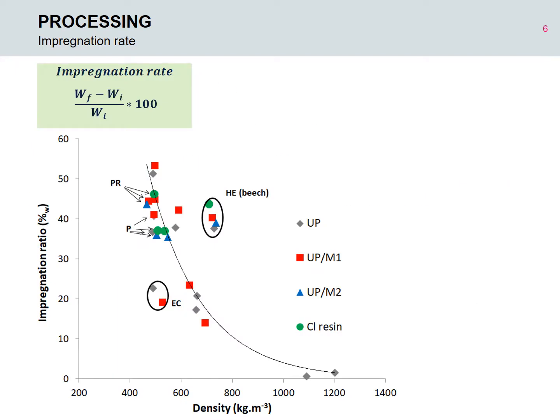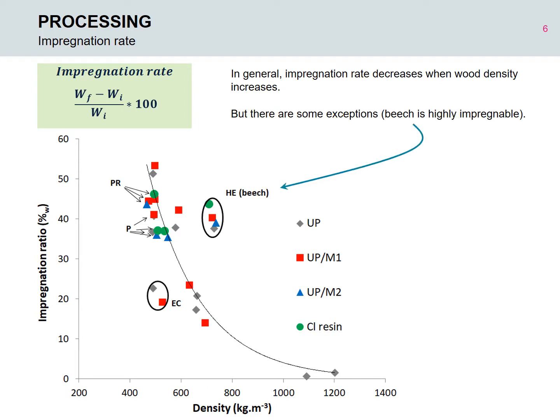We have measured the impregnation ratio of all our samples. The first observation is that the ratio decreases when wood density increases. Especially, it is very low for very high density woods, so the method is not suitable for these woods. Note that some woods like beech have a quite high density but remain very impregnable.